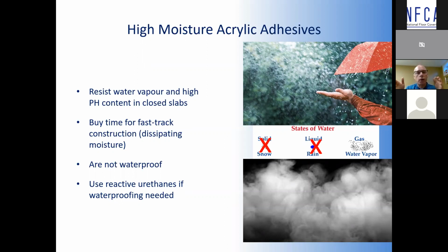If it's an actual problem, so if you have hydrostatic pressure or water coming up through the concrete, that is not what high moisture acrylic adhesives are meant to handle. They're really only meant to handle moisture vapor that is existing in the concrete itself, and they are not waterproof. So they are very highly water resistant. However, they're not waterproof. So if you need a waterproof adhesive, you're going to be going to a reactive urethane, or even a silane modified is going to give you waterproofing.